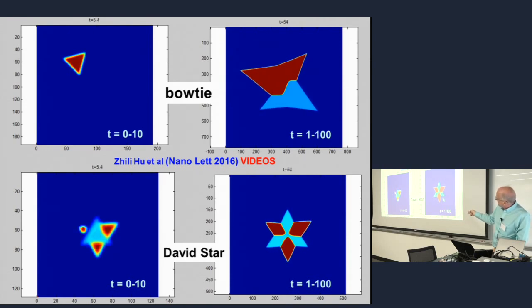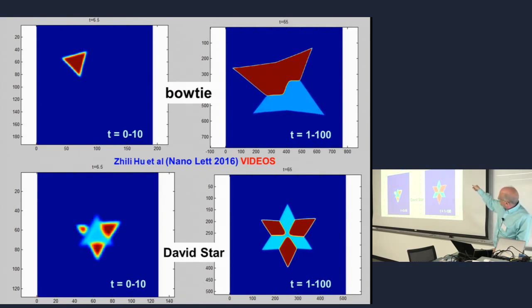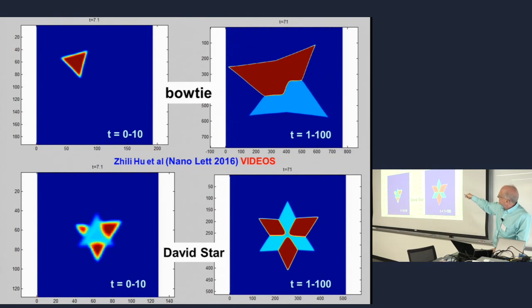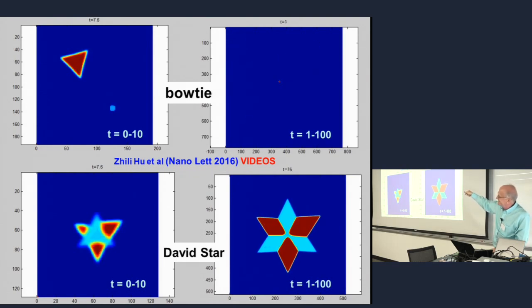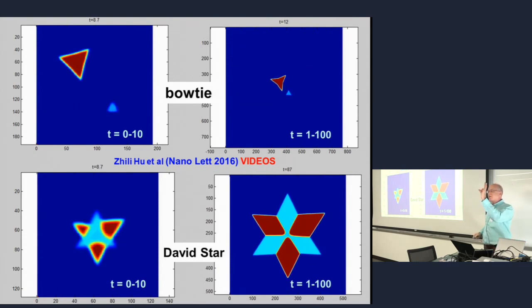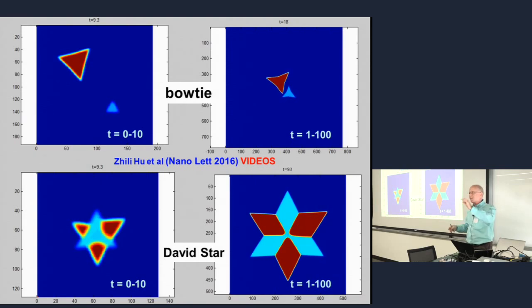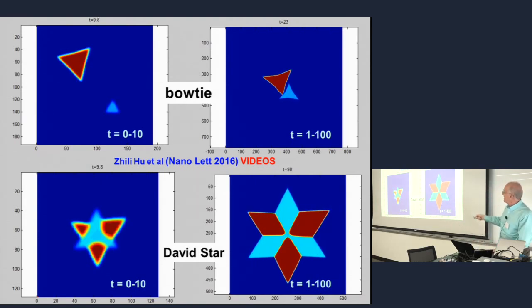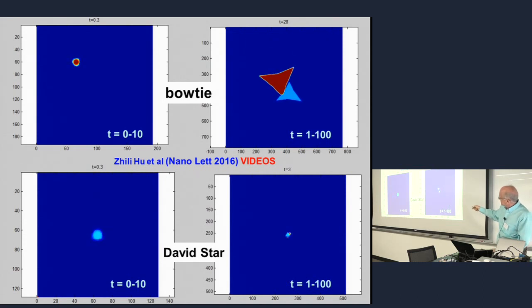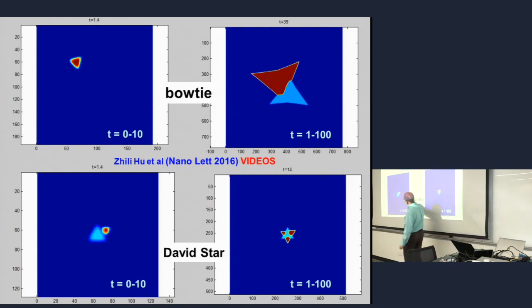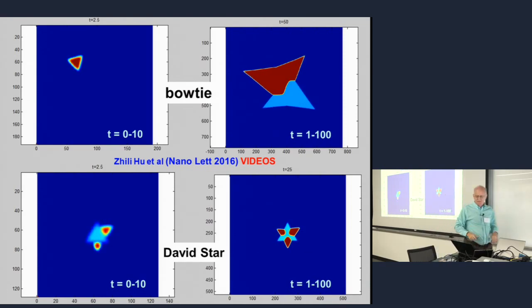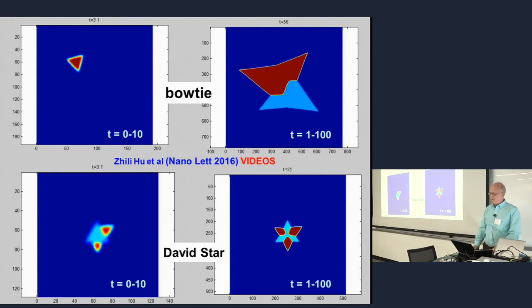This is the simulation, this is the same, but very slow, very fast. Very slow here, very fast here, just to show you results. You see here it's still emerging. You still don't have a second seed. Now the second seed just appeared. We start from a circle. Of course, the model takes care of it, forms triangles. We start from a circle. It's not pre-made. And then it gives you this structure. This symmetry recovers beautifully. It doesn't matter how you position them. They can be pretty randomly positioned here. But because it grows out of the scale, then you don't see. At the end, it looks like a very symmetric, beautiful structure, like in many experiments.